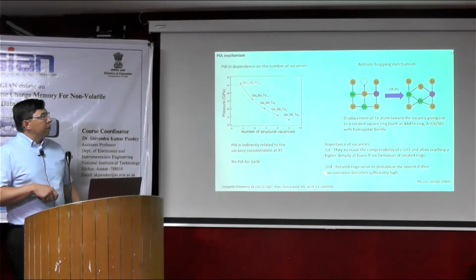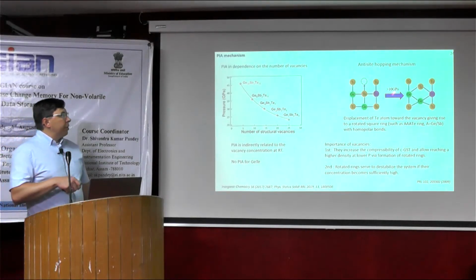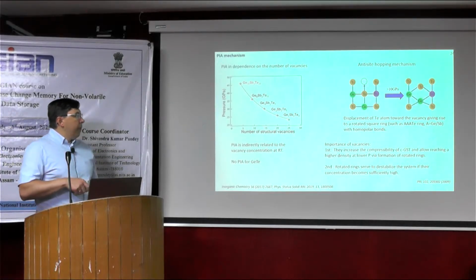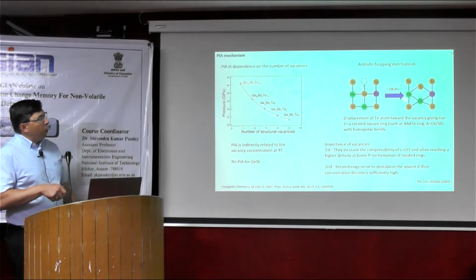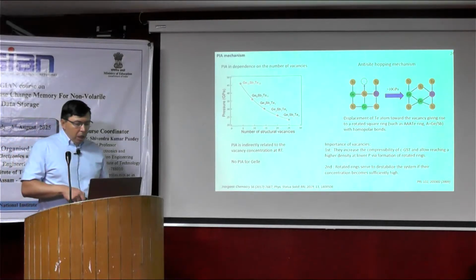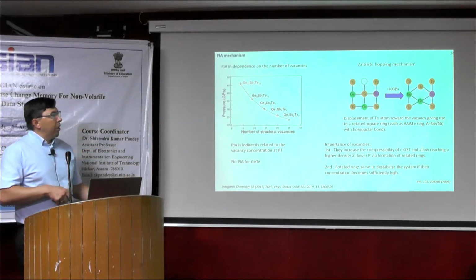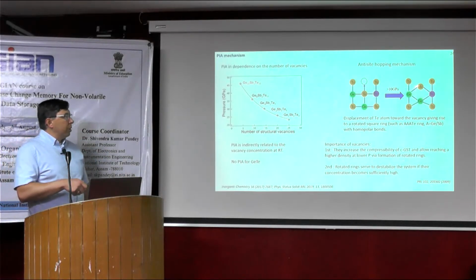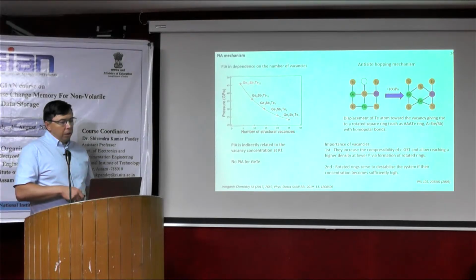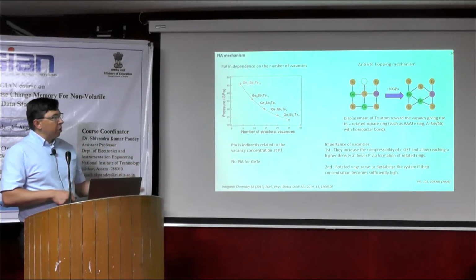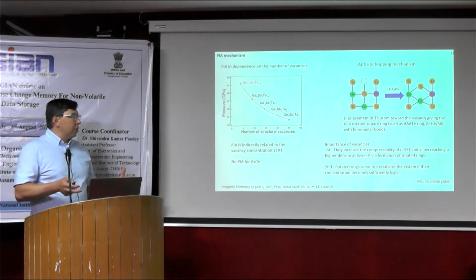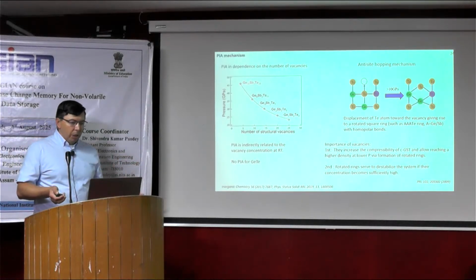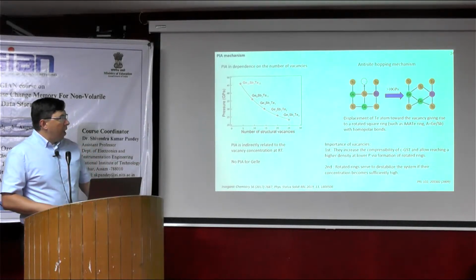And second, if such rings form, due to these homopolar bonds, they destabilize the system. And if the number of such rings increases and is sufficiently high, then the system becomes destabilized and transforms to the amorphous state.